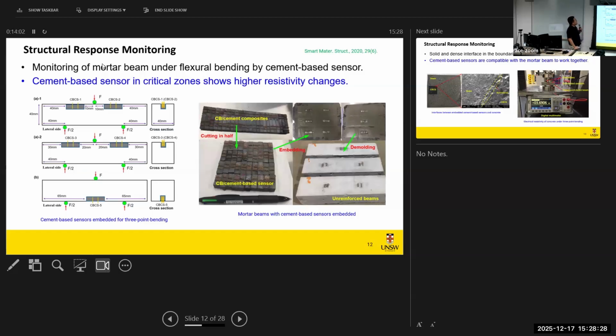Here, I would like to introduce the application of the cement-based sensors to monitoring structural responses. Here you can see a mortar beam under flexural bending with cement-based sensors embedded. The cement-based sensors are embedded in the critical zones of compression and tension of the beam. It means when we use nanomaterials for cement-based sensors, we do not use the nanomaterials for the whole element or the whole components. We just use them for the critical zones, where there is large stress and more potential for cracks. Here you can see these are the compression and tension zones.